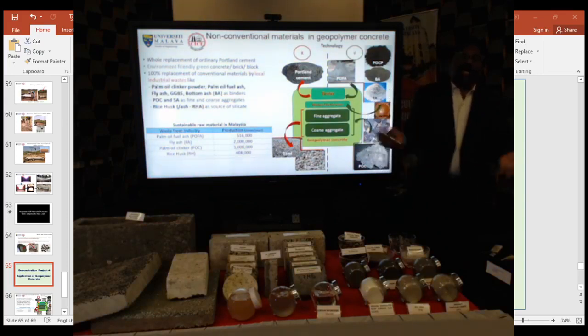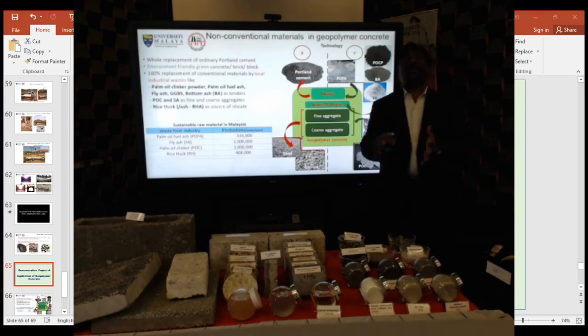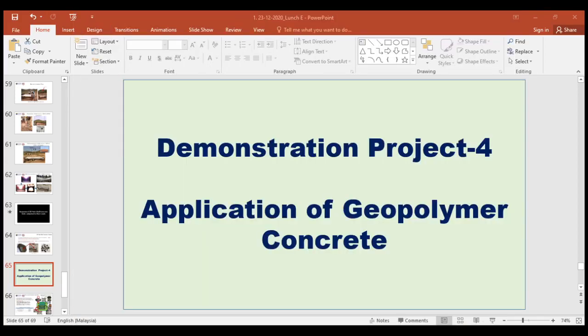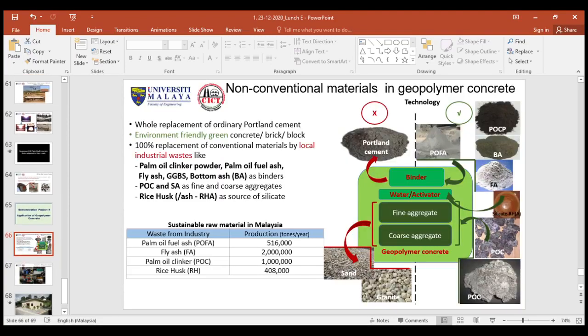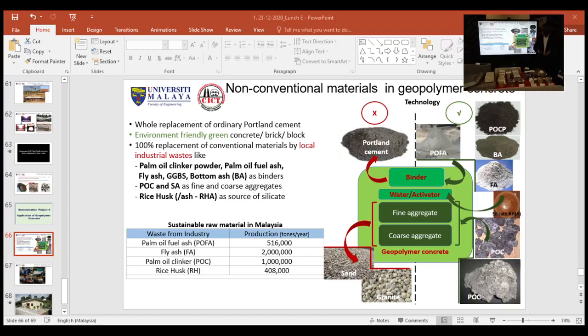Replace the cement wholly, 100%. We don't want to use ordinary Portland cement. So we need other alternative materials. As I mentioned in the beginning, fly ash is one of the sustainable materials. So far we have been using it, and we have ground granulated blast furnace slag, simply called slag. We do have palm oil fuel ash, we have palm oil clinker ash, we have also bottom ash. In addition we have metakaolin, which we can also utilize.